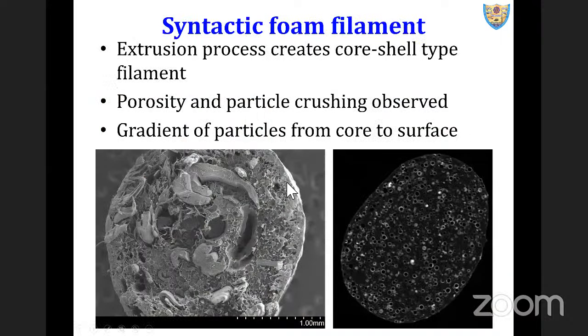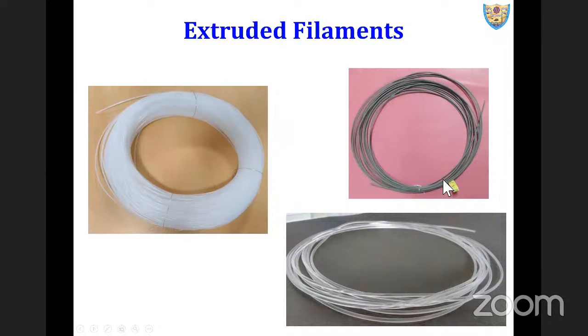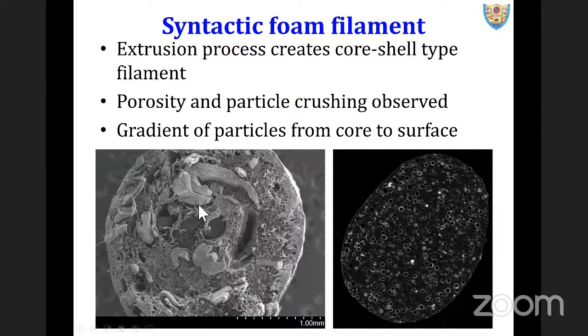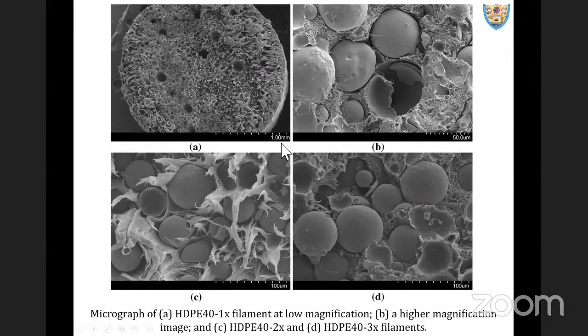As part of the syntactic foam development pertaining to this filament, I'm going to talk now. We did extrusion, and this is the first sample of the filament, which is not a good sample. The reason is there is gradation of cenospheres from core to the end. The diameter is also variable. This is a micro CT scan which clearly shows the cross section. So that means we need to modify or optimize or find suitable extrusion parameters. We did so, and finally we got these good filaments which are 2.85 within plus minus 50 microns.